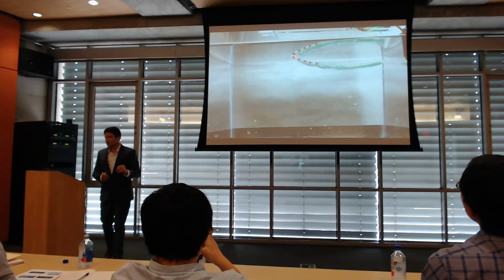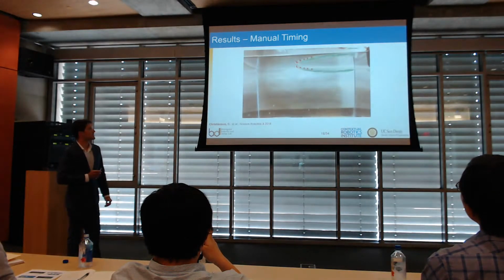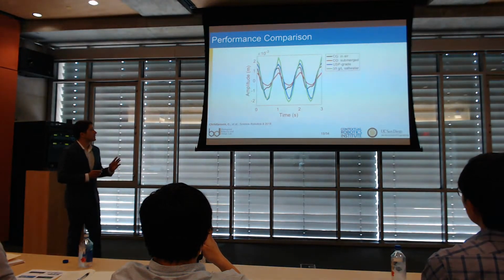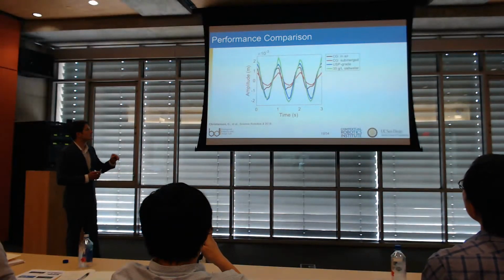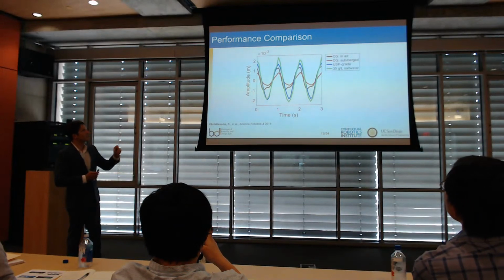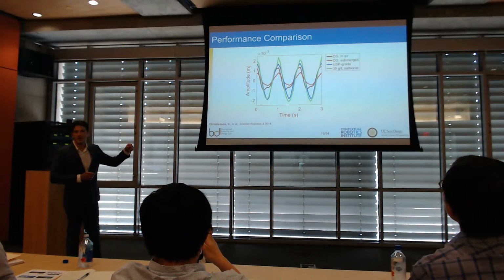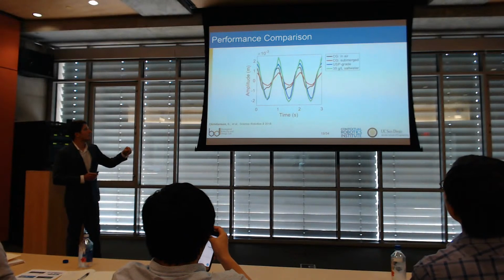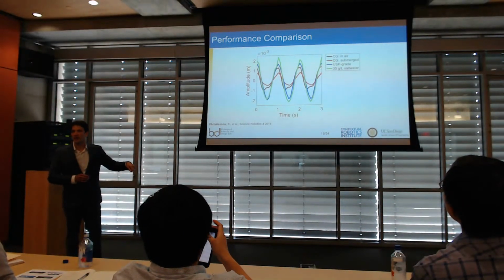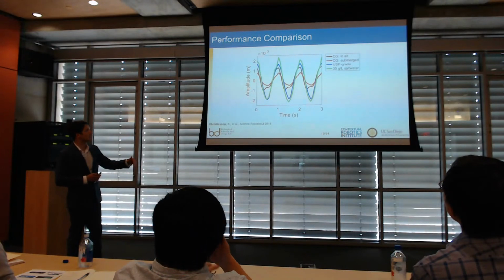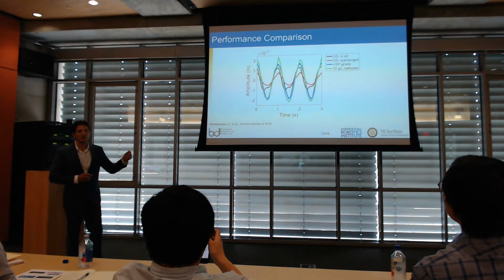For that, I also wanted to compare it to carbon grease, to see how water compares to carbon grease for an electrode. So I made 4 different actuators. The first 2, black and red, are carbon grease. The first one is in air, so there's no fluid damping. The red one is when we put the carbon grease actuator into water, and the amplitude becomes a little bit smaller. And then I compared USP grade, which is very pure water, as opposed to very salty water.